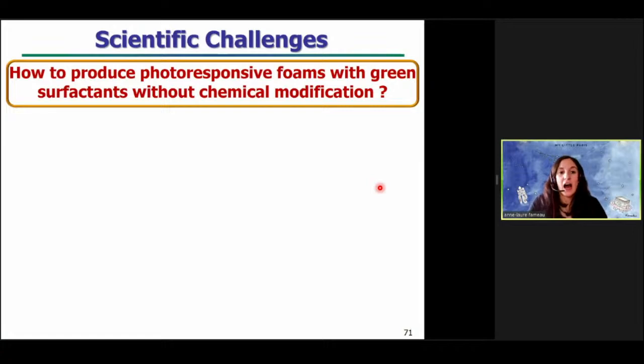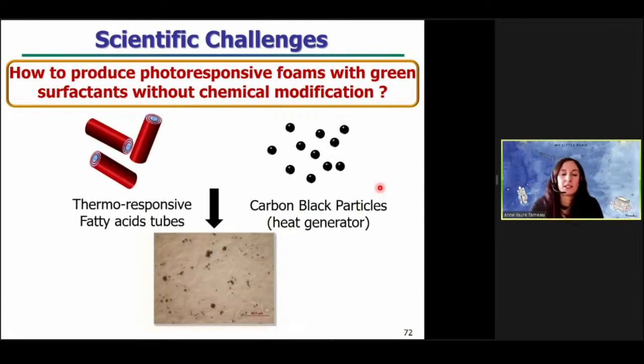Then the next scientific challenge was how to produce photoresponsive foams based on green surfactants without chemical modification. Why were we interested in developing photoresponsive foams? It's because light as an external stimulus has many advantages in comparison to temperature, because with light you can direct light at a precise location with micrometer scale resolution, and you don't need to touch the sample. So our strategy was to use a chemical engineering approach and to use the thermoresponsive fatty acid tubes that I just showed you previously with specific colloidal particles, such as carbon black particles. Why these particles? Because they are known to act as heat generators. That is to say that they can absorb UV light, and due to a photothermal conversion effect, they can transform the light into heat. And so for this system, we use tubes with a temperature transition around 45 degrees.